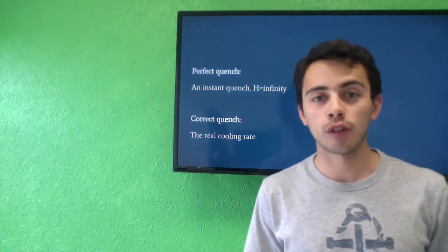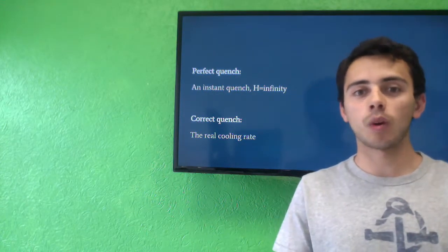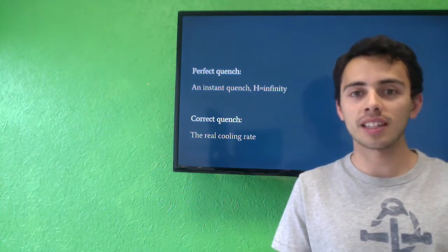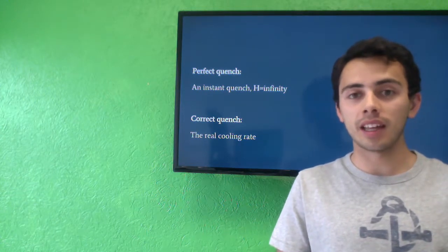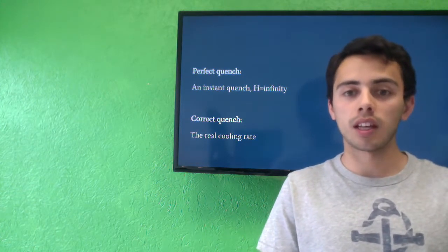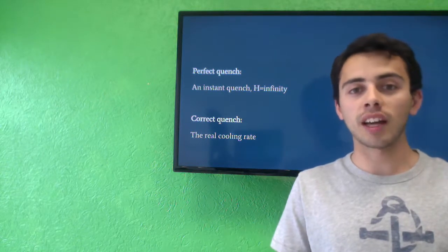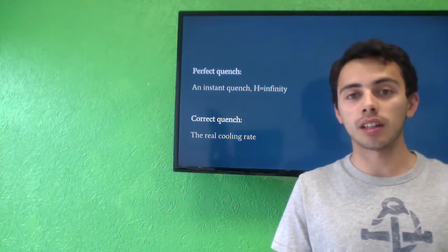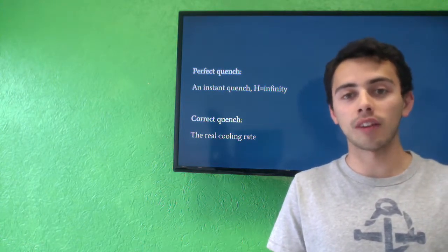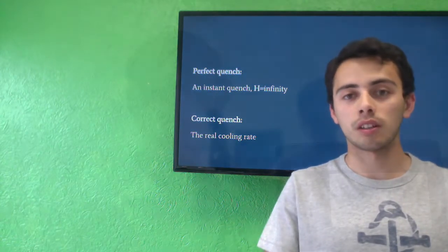A perfect quench refers to a quench that is immediate. It's when the whole piece, the surface and the inside, cools immediately and the whole phase is transformed at once. In contrast, a correct quench is the actual quench with a real cooling rate, not an infinitely high cooling rate.